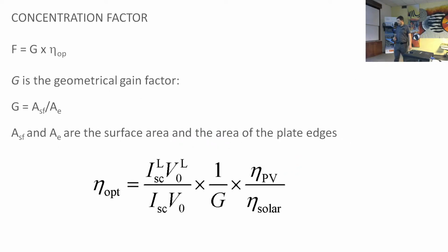If you go to a real luminescent solar concentrator, you also need to consider the geometrical gain factor, in which this value is the surface area that collects light divided by the area in which you have the photovoltaic cell. Okay? If the plane is very large, then the surface area will be larger, and so this G factor will increase, which in turn will increase the efficiency of the luminescence of the device. Okay? And this is also a way to calculate the optical efficiency of your system.